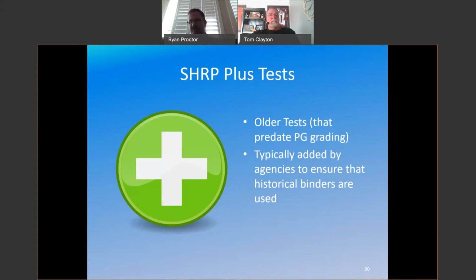Before CDOT had PG 64-28, they had AC20P and AC20R. I should say that really covers our whole region. When they went to PG 64-28, they still liked some of the performance they were getting from these tests, and they left them in place. And if you look across the country, that's usually what you'll see: people like the performance that these SHRP plus specs gave them. So what they might do is specify, like in CDOT's case, a 64-28, and then add some of these other tests.